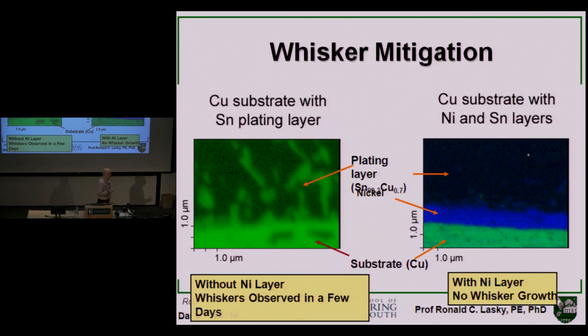But this is enough of a concern that what people have done to show that this doesn't solve the problem is if you then take something like this and put it in a situation where other things can cause stress in the tin, pretty much it's just, if you induce compressive stresses, you might grow tin whiskers. Like literally even just putting a mechanical clamp up here and clamping and pushing down on it could cause tin whiskers to sprout. And thermocycling or something like that.